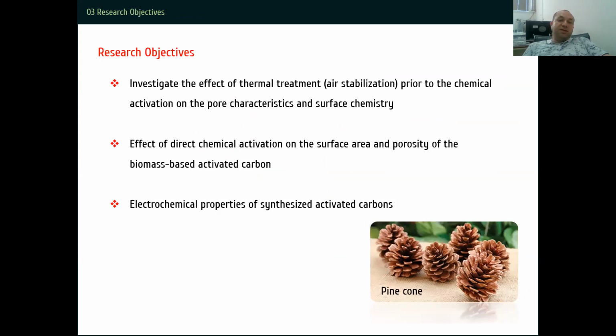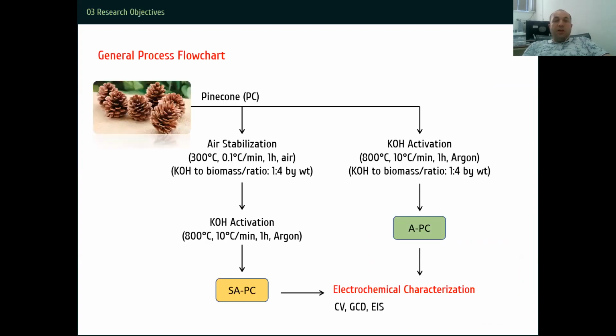We tried to investigate the effects of thermal treatment or air stabilization prior to the chemical activation on the pore characteristics, the effect of direct chemical activation, KOH activation, on the surface area and porosity of the biomass-based activated carbon, and at last, the electrochemical properties of synthesized activated carbons.